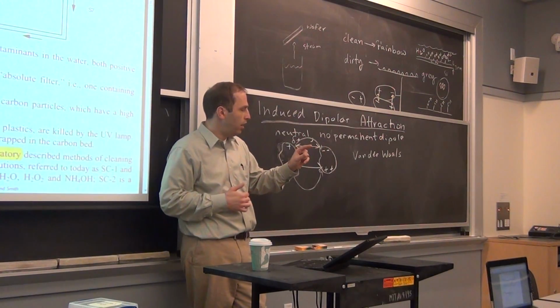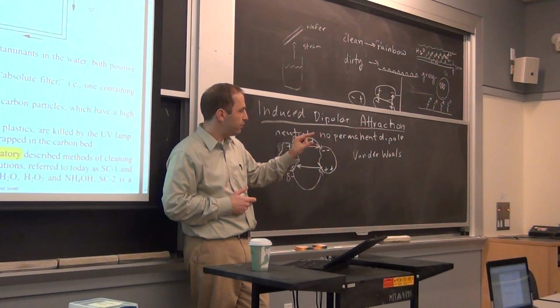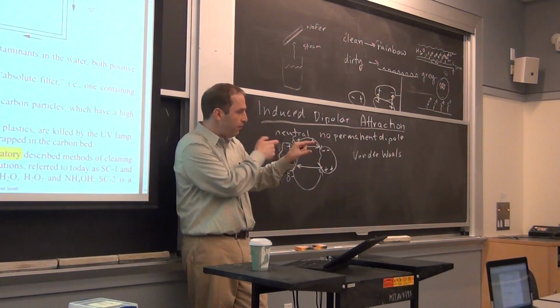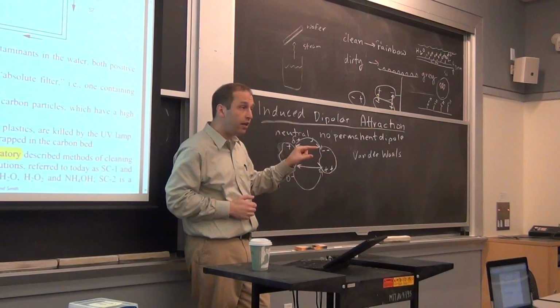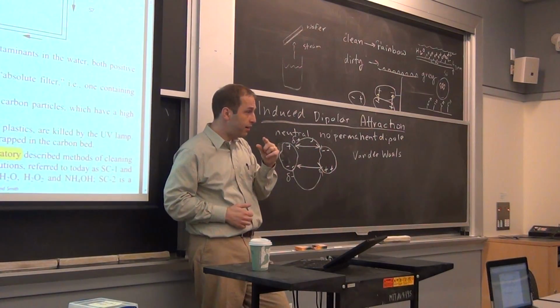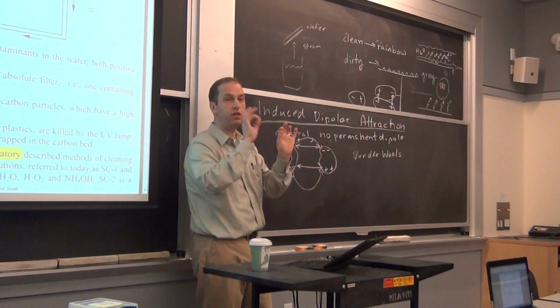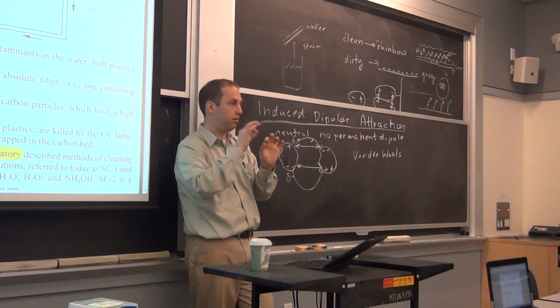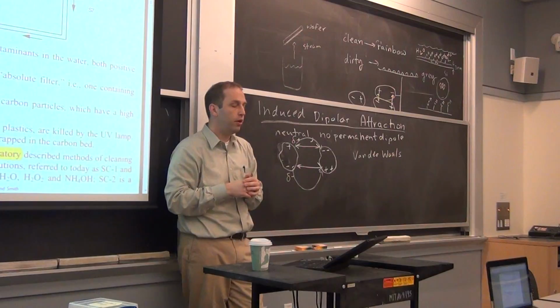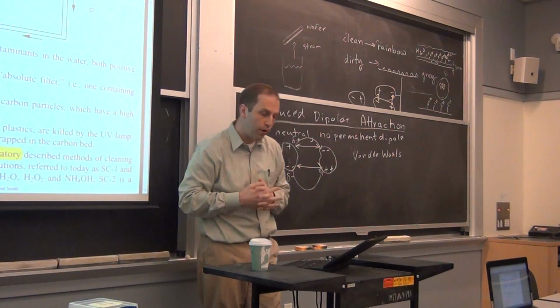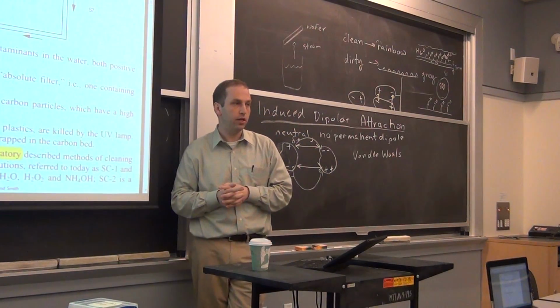I remember in grad school we'd have these experiences with a clean wafer, and then you blow the dust off of it, and then if you do the breath test or the steam nucleation test, you see the lines of the nitrogen where it deposited junk on the wafer. So blowing it with nitrogen is something you should do only in extreme circumstances.